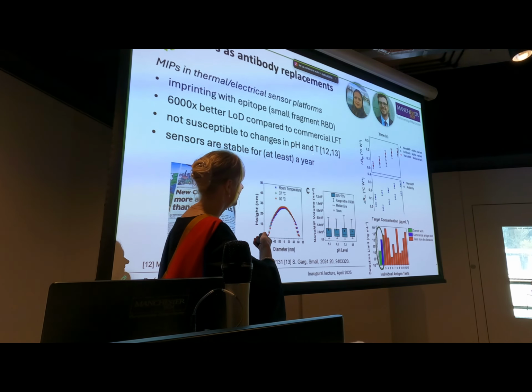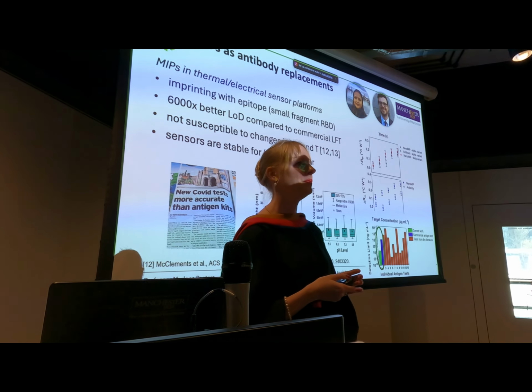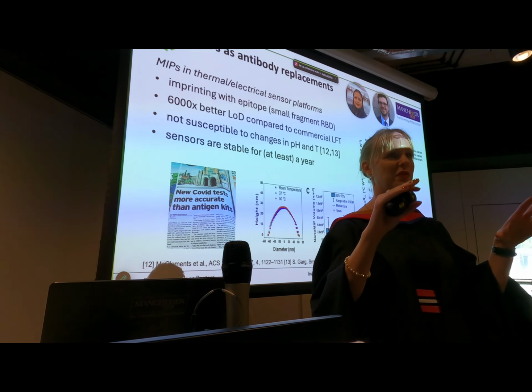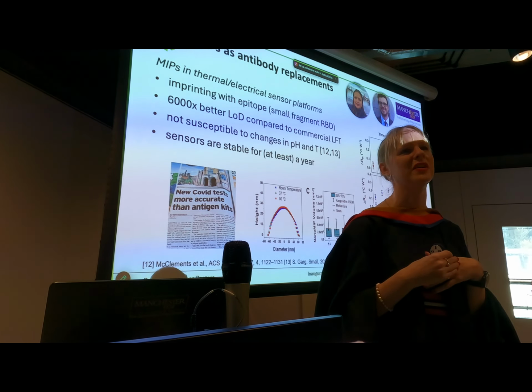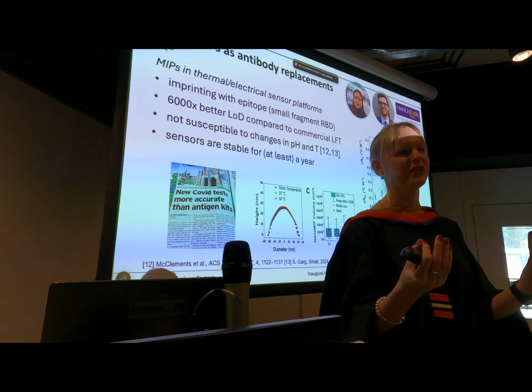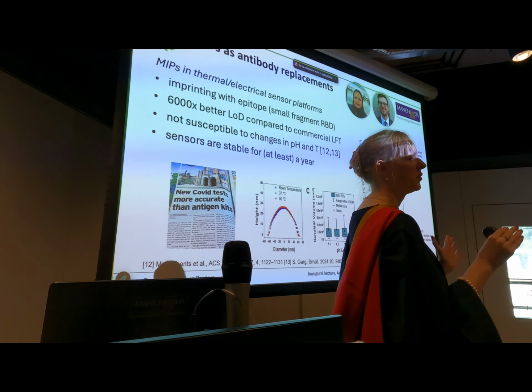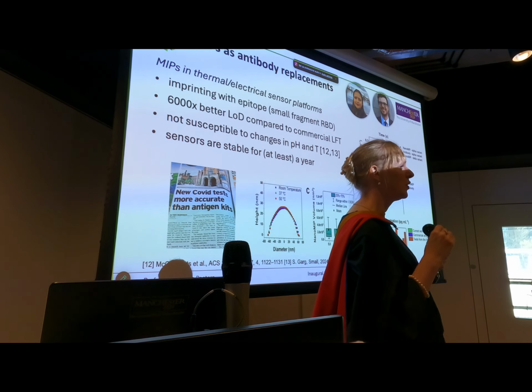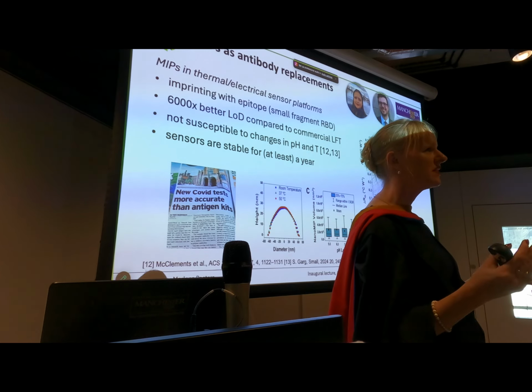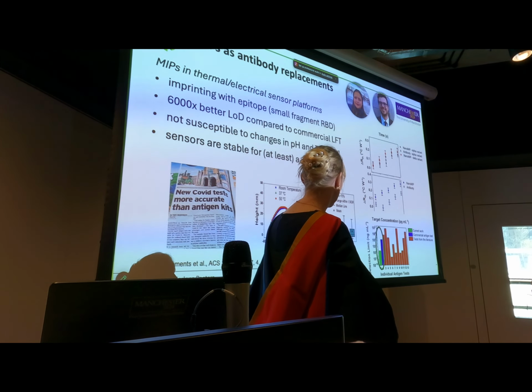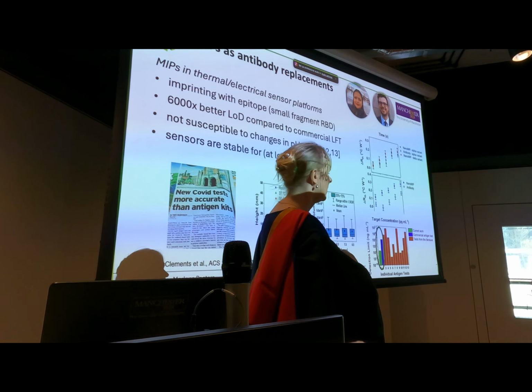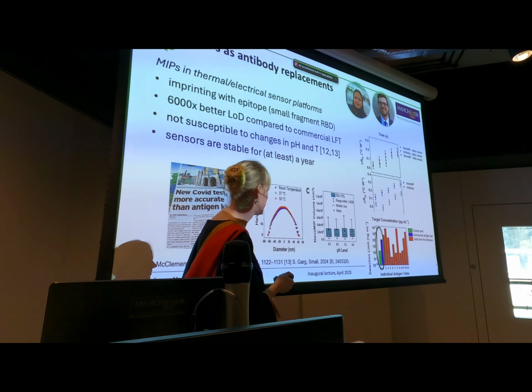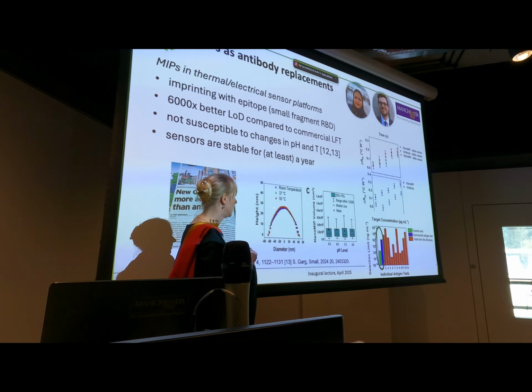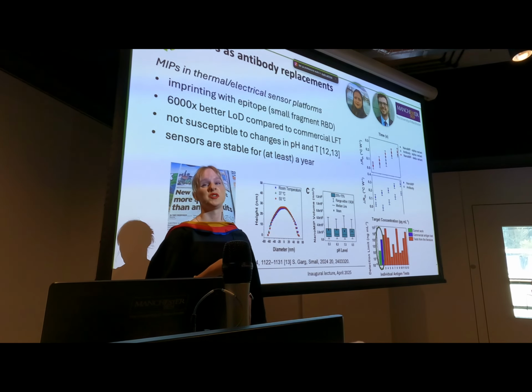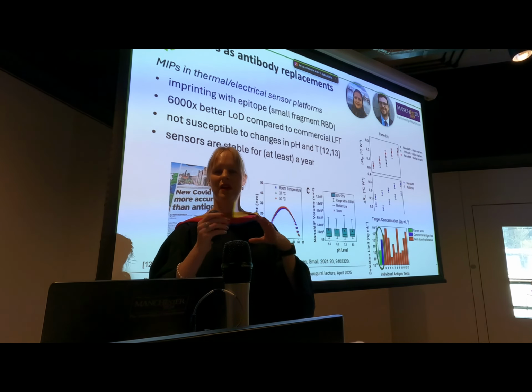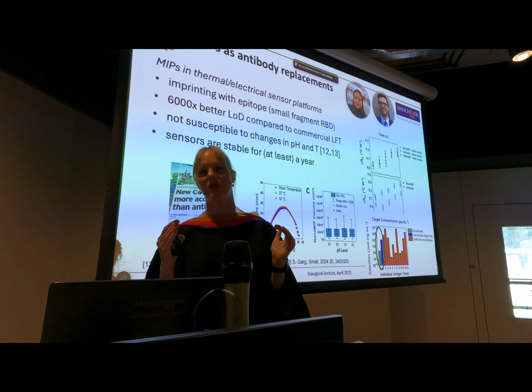But the key thing here, and remember that I showed you this example of these lateral flow tests, which were positive because of having either Diet Coke or brandy or vodka. We could throw anything we wanted at our sensors. So basically, we could pasteurize it by having a very acidic or basic pH. We could heat it up, and this is what these particles look like. So first of all, you can see the particles, this is just the diameter. So you heat it up to 50 degrees, which is basically the limit of our setup, and nothing really changes in the shape of the particles.